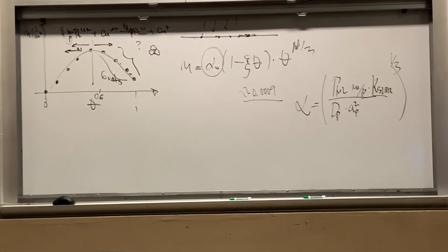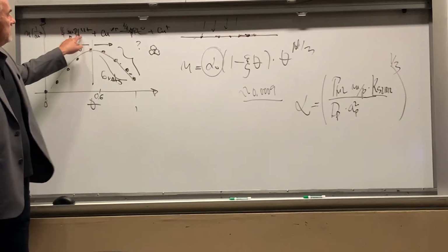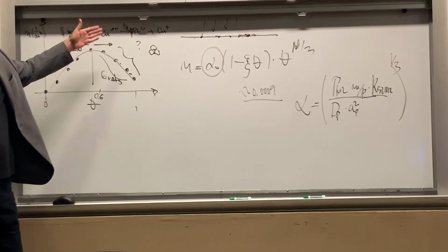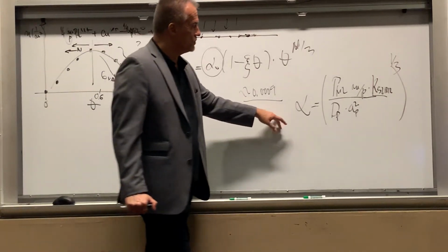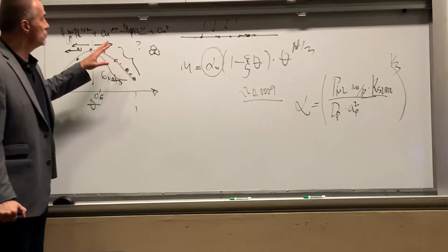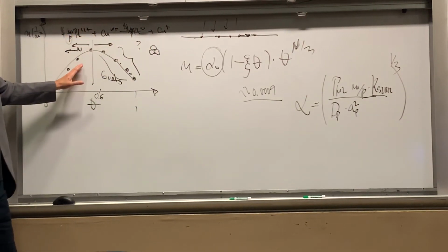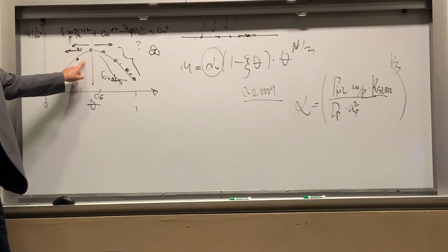All right, the bottom line is this. Choosing a certain kind of chemistry of the solution allows you to control, to some extent, alpha through the N_p ratio, but more importantly, through the order of the reaction, as we discussed, which affects what coverage gives you the maximum nucleation density.